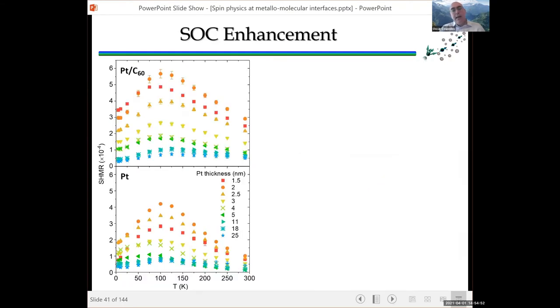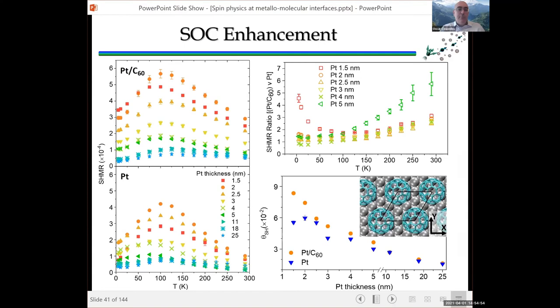How much is it enhanced? Well, up to a factor 5 or 6, as I was saying before, but typically between 50 and 100%, so 1.5 to a factor 2. This can be interpreted as an enhancement in the spin Hall angle, so perhaps a means to reduce the spin current in spin transfer torque devices in the future, perhaps.